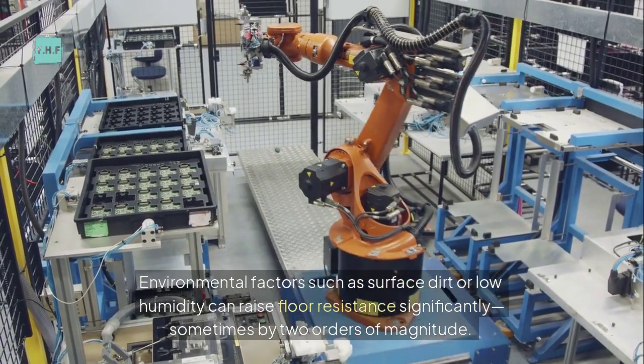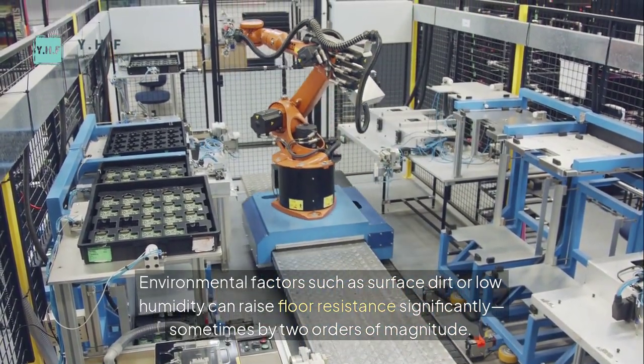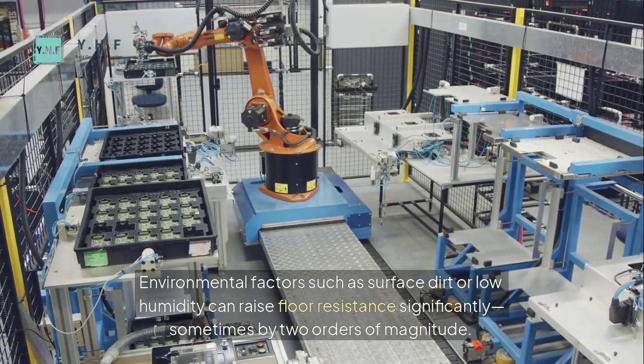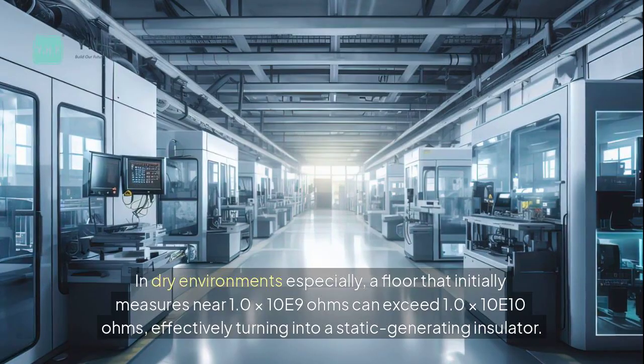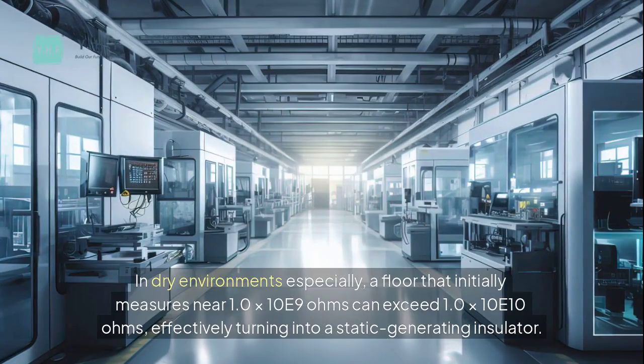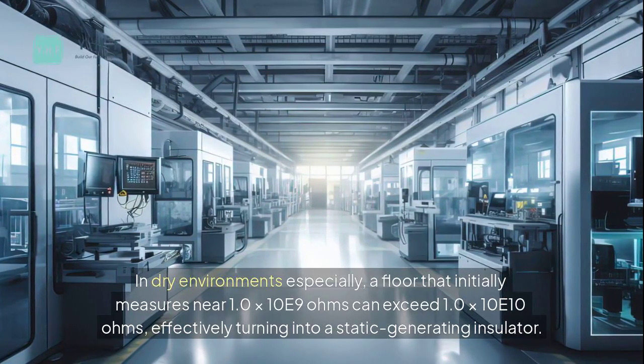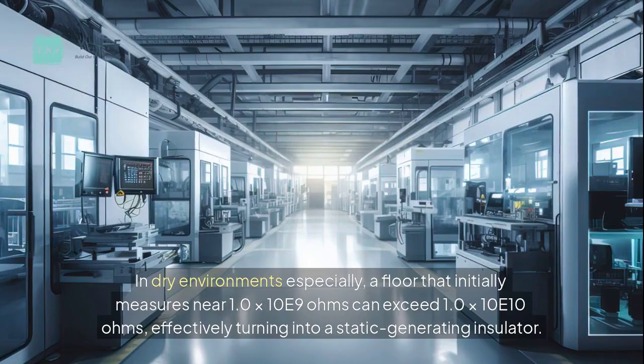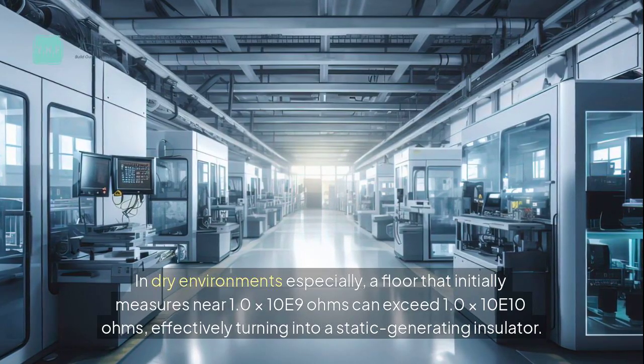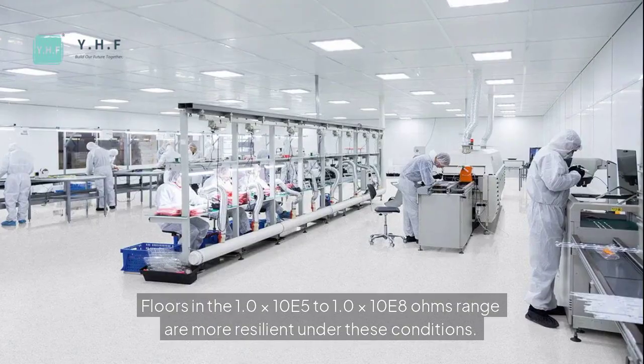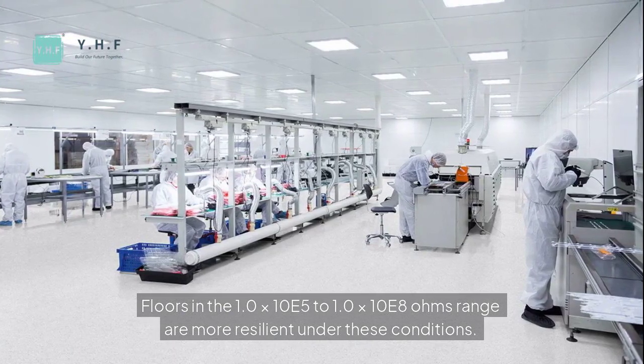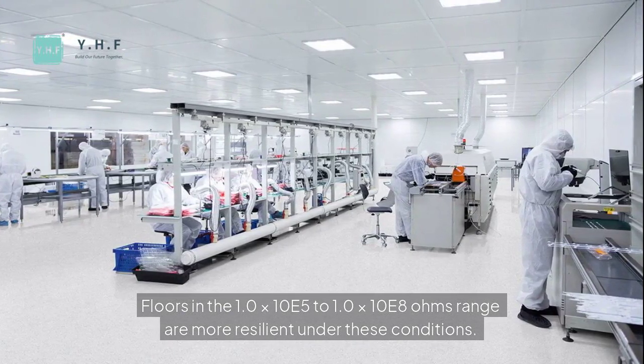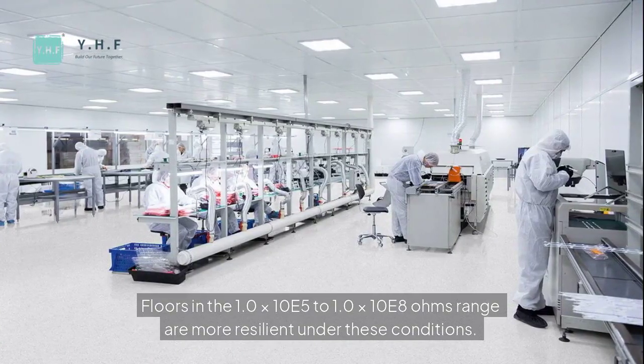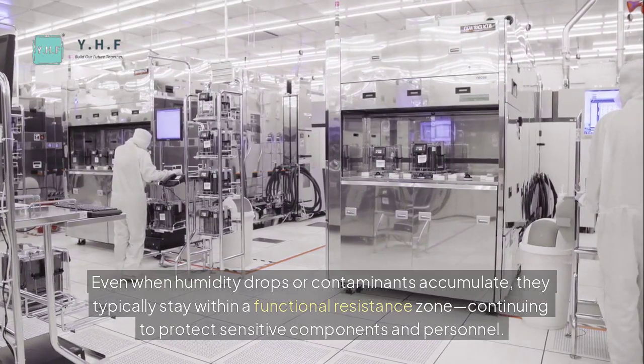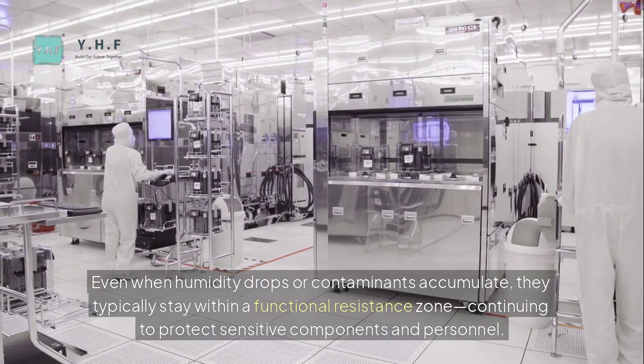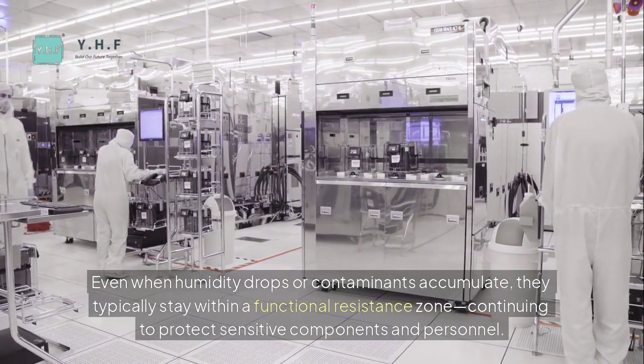Environmental factors such as surface dirt or low humidity can raise floor resistance significantly, sometimes by 2 orders of magnitude. In dry environments especially, a floor that initially measures near 1.0 × 10^9 ohms can exceed 1.0 × 10^10 ohms, effectively turning into a static generating insulator. Floors in the 1.0 × 10^5 to 1.0 × 10^8 ohms range are more resilient under these conditions. Even when humidity drops or contaminants accumulate, they typically stay within a functional resistance zone, continuing to protect sensitive components